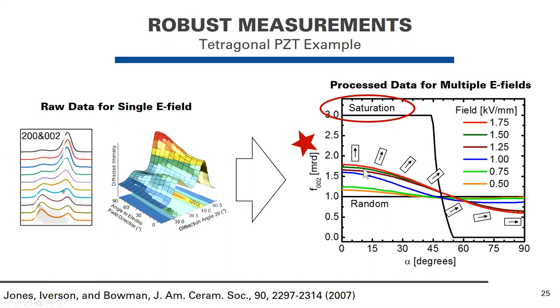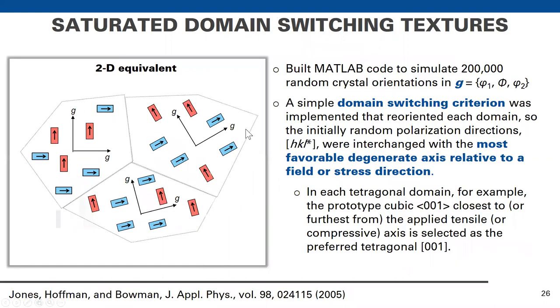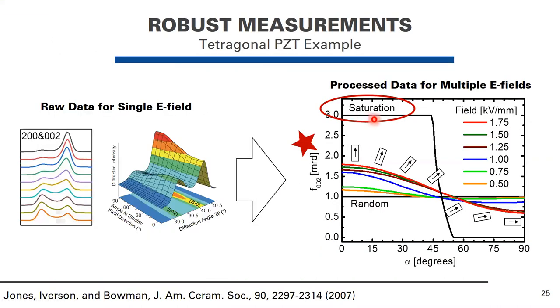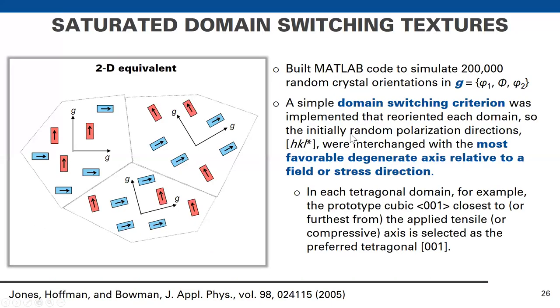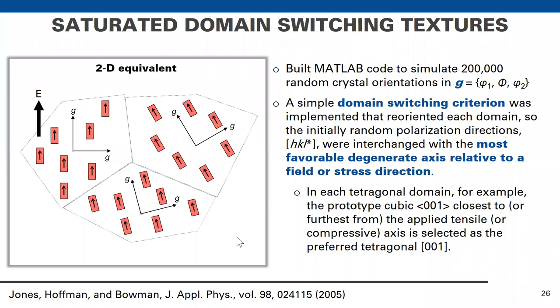Okay. Now, this plot also introduces this idea that we know the maximum value of possible domain orientations and the pole figure that represents that. So again, as a grad student, I was playing around in MATLAB and I decided that I wanted to model this type of phenomena. Okay? The situation where all of the domains aligned to the fullest possible extent. And so going back to this simplified schematic that I was showing before, you could consider a situation where every single possible orientation reorients to the most favorable one.